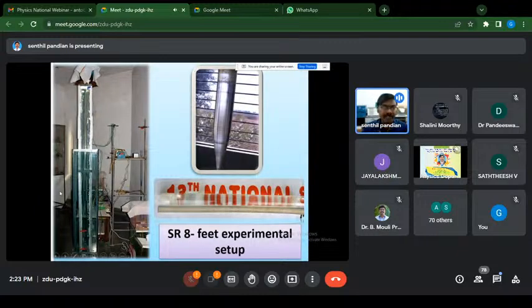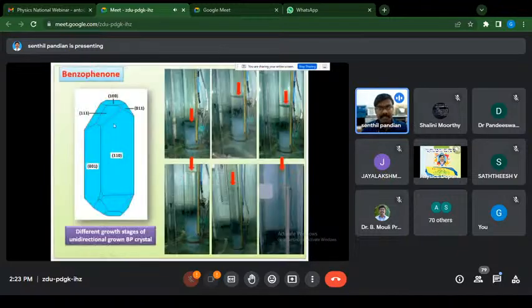This is our actual 8 feet experimental setup of this SR method. The benzophenone seed crystal is mounted here at the bottom of the glass sample, and we have maintained one heating coil at the bottom of the glass sample and one heating coil at the top of this glass sample, and we have poured the saturated solution. When the crystal is growing from bottom to top, we have also increased the heating coil from bottom to top. So this much transparent crystal can be grown by this SR method. This is the transparent benzophenone single crystal grown by this SR method.